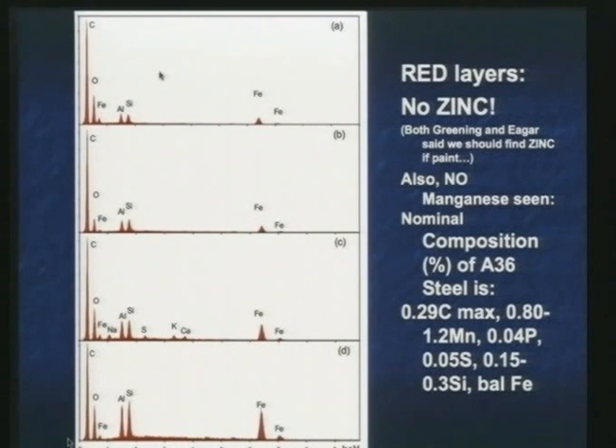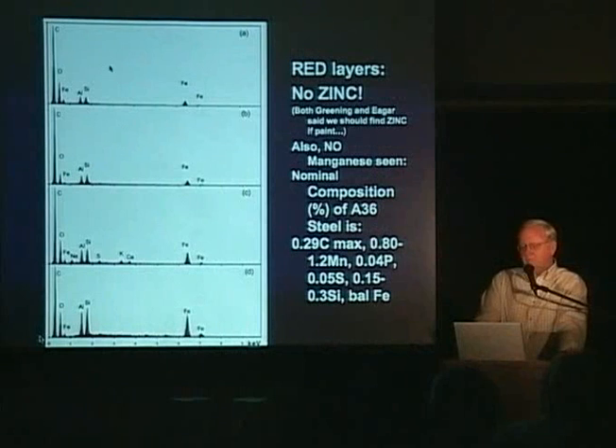You look at that bottom plot, for example. These are the 4 samples showing essentially the same chemical signature. The principal elements are the same. Anyway, no manganese and no zinc. It's starting to not look like steel from the buildings because of the lack of manganese, and not like paint either, not like primer paint, as we'll see, because of the lack of zinc. Notice the elements that are there: carbon, a significant peak, oxygen, aluminum, silicon, and iron.